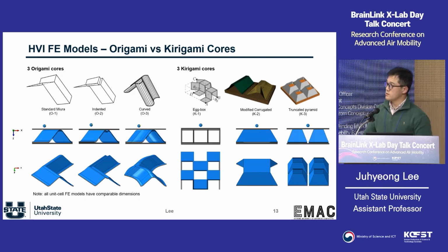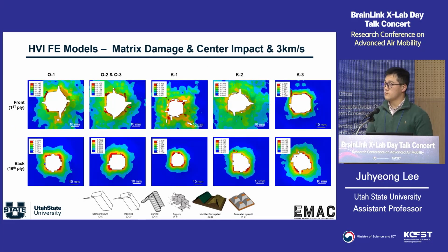And also, when you design different origami cores, I selected 3 representative origami cores, starting from standard Miura, and indented and curved. And also, I considered 3 different cores: egg box and the corrugated. So these are all the finite element meshes that we created with my student. And then we run the simulation to predict the fiber, the matrix, and all the delamination failure. So simply, if you're looking at the holes, these are fully damaged areas. Of course, a smaller hole means smaller damage, which is relatively recommended when you design your part.